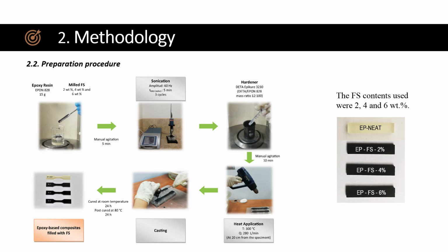The composites were obtained following the procedure shown in the following schematic. In a determined amount of epoxy resin, these sands were added. The sand contents used were 2, 4, and 6% in weight. Then, these sands were dispersed by sonication in an ice bath. Afterwards, the curing agent was added to the as-prepared dispersion and manually stirred for 5 minutes. The composites were shaped by casting in acrylic molds.